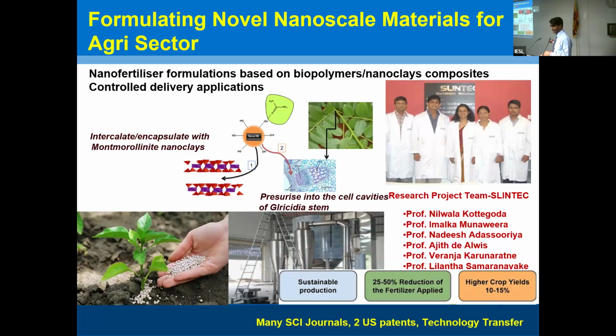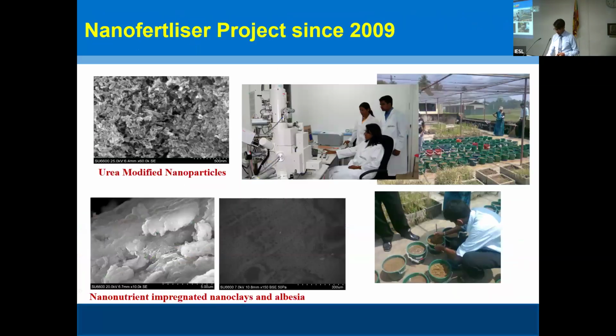So we started as graduate students, and you see here, we could achieve a 25 to 50% reduction of fertilizer application, and of course we could improve the crop yields by 10 to 15%. And apparently the project continued even though we left the place for our doctoral studies, and they even commissioned a reactor to produce these systems in bulk. And then here we could achieve 2 US patents, and this is some images from this project.